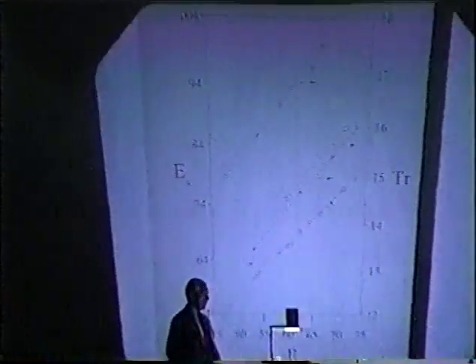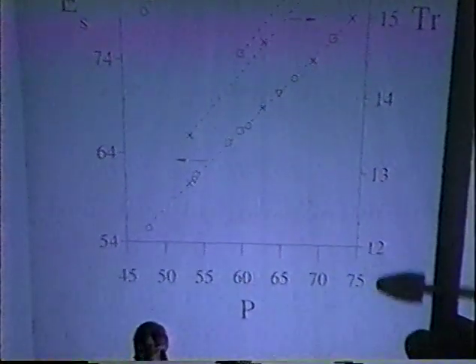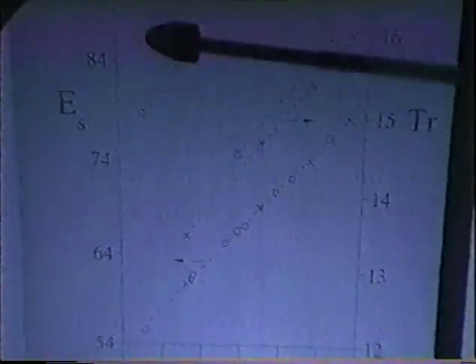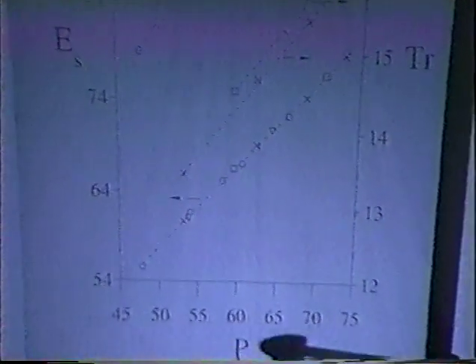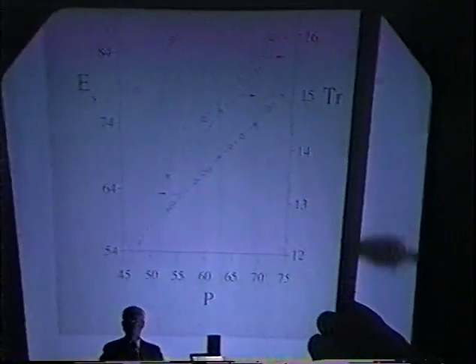It was necessary to confirm that the CFEX calorimeter is in fact insensitive to the spatial distribution of thermal power. I did that to my satisfaction. It's also very important to confirm that it's insensitive to the gas-phase composition. And this graph shows you two things. First, consider the bottom curve, which is the CFEX signal, E sub S, as a function of input power in watts. The E sub S is in millivolts, as you see, 84, 74, and so forth. Input power is 50, 55, 60, and so forth, up to 75 watts.